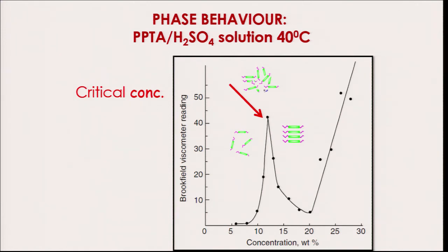There is a sudden drop in viscosity beyond this concentration, which is attributed to the domain formation. And surprisingly, this concentration is also known as the critical concentration. But please note, this critical concentration is different from the critical concentration in the case of PE gel fibers. This critical concentration depends upon the temperature of the solution and the molecular weight of the polymer. If I have higher molecular weight, this behavior would happen at a lower concentration. The critical concentration would come down. If I increase the temperature, again the critical concentration will come down. Okay? And if I do the reverse, the critical concentration will increase.